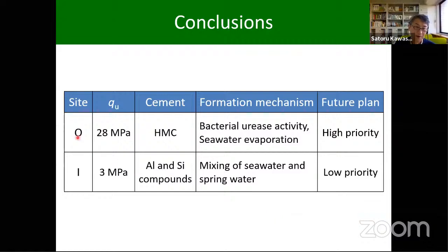This is the conclusion. Site O, the Okinawa site, has an unconfined compressive strength of around 28 megapascal, and the main cement material is high Mg calcite. The formation mechanism is bacterial urease activity and seawater evaporation. On the other hand, site I is smaller than site O, at 3 megapascal in unconfined compressive strength, and the main cement material is alumina and silica. The formation mechanism is mainly a mixing of seawater and spring water.